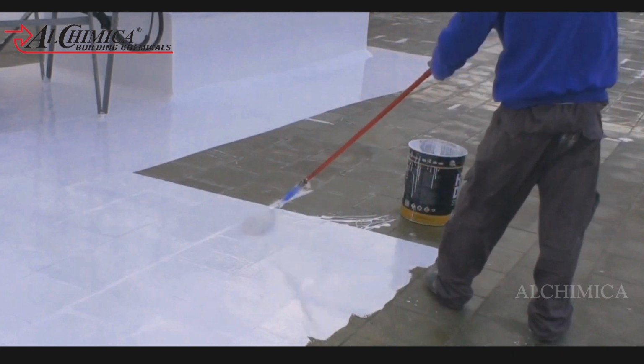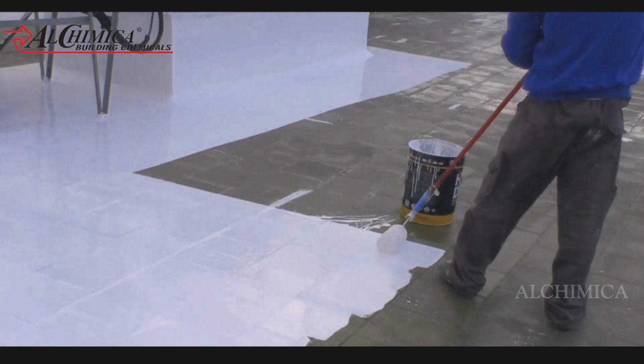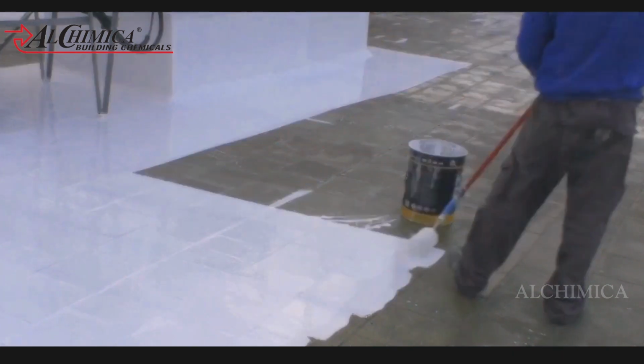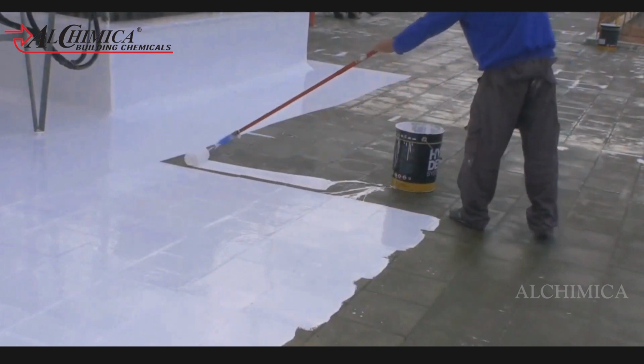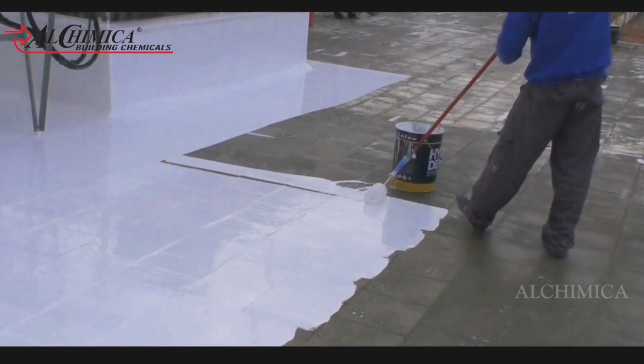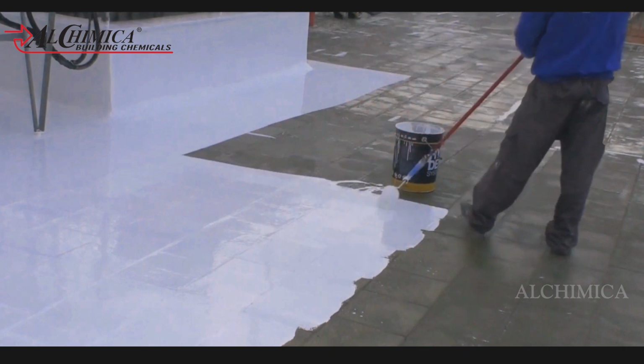The tack-free time for this coating is between 3 to 4 hours. However, the time gap between 2 coats should not exceed 24 to 48 hours.